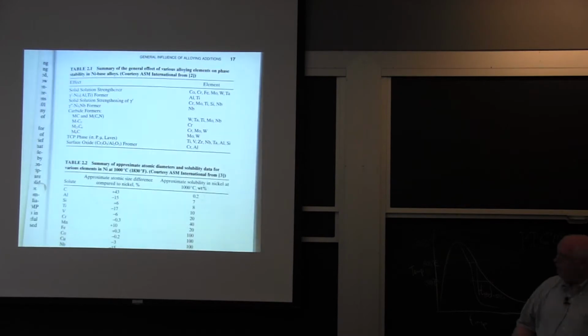Anyway, so these different alloys that go into these things, the solid solution strengtheners are cobalt, chrome, iron, molybdenum, tungsten, tantalum. The precipitation hardening, which they call gamma prime, is the phase. Aluminum and titanium. It turns out niobium also does that, but it's a gamma double prime, slightly different crystal structure. Solid solution strengthener is these alloys. And then they have all these carbides. Some things, chrome will form a carbide, tungsten will form a carbide, molybdenum will form carbides, niobium. So they throw in different carbide formers to harden things.